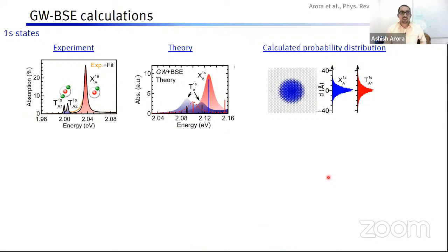First, we go to our theory partners, and they do GW-BSE calculations. They calculate the absorption spectra and find the probability distributions of various features in the absorption spectra. Now, this is experiment and this is theory. In theory, they also find that there have to be two types of trions, or ground states of trions, and one exciton, which agrees well with our experiment, and the probability distribution is spherical without any node or anything. So this is a hydrogen-like 1s state.